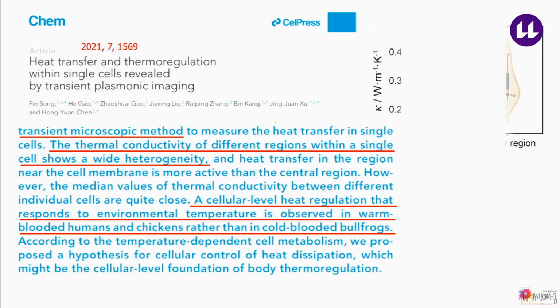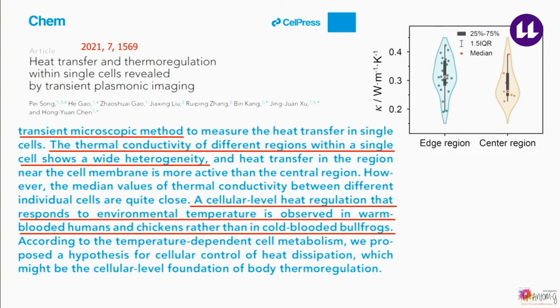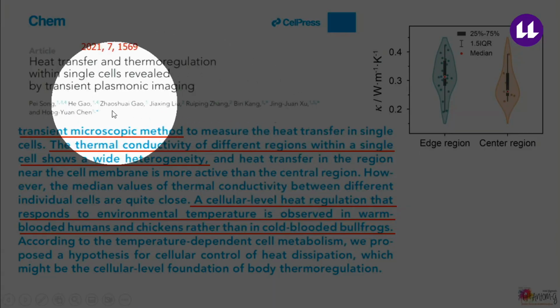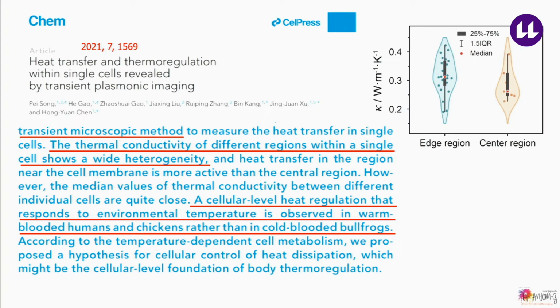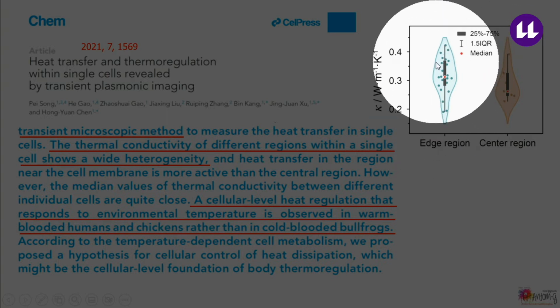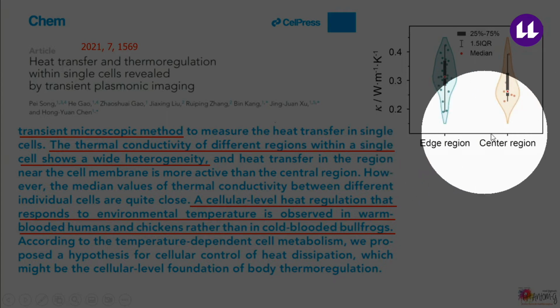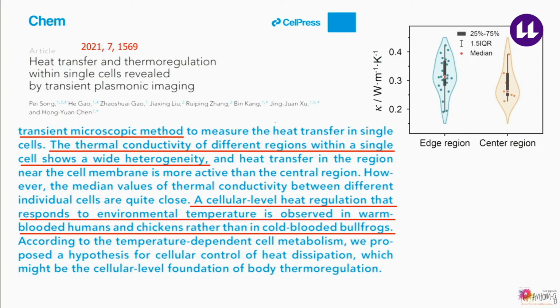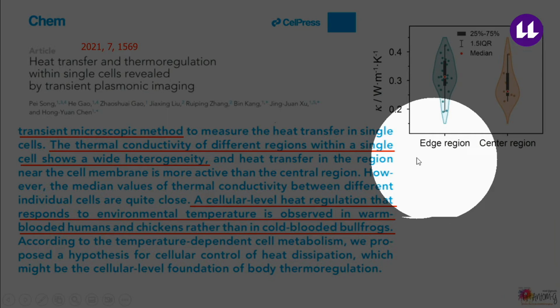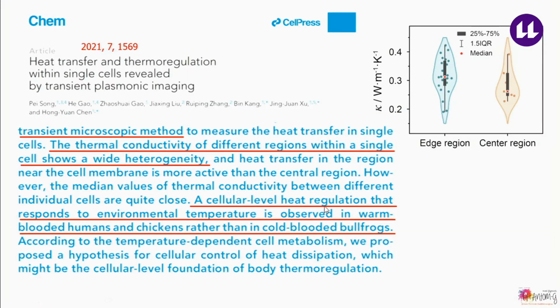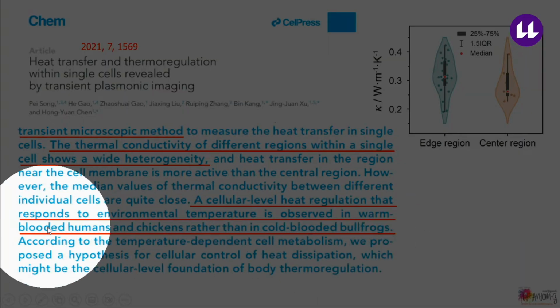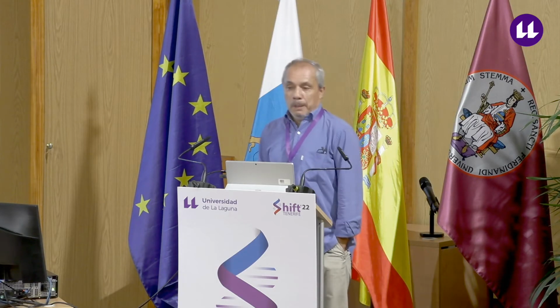Another interesting example that appeared recently is this group of Chinese researchers who used a transient microscopic method to measure the heat transfer in single cells, and they found, first, a dispersion of the thermal conductivity, and that dispersion is really dependent on the location in which the measurements were done. And the second interesting thing is that they report a cellular level heat regulation that responds to changes in the surrounding temperature, and this is observed in warm-blooded organisms and not in cold-blooded ones.